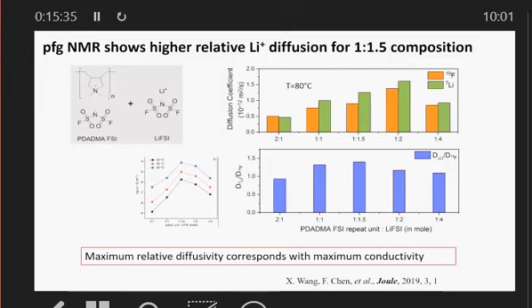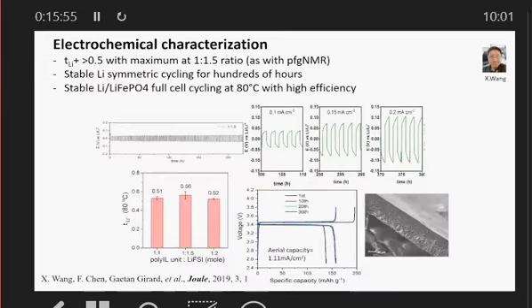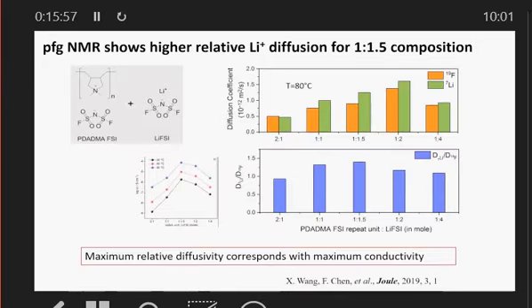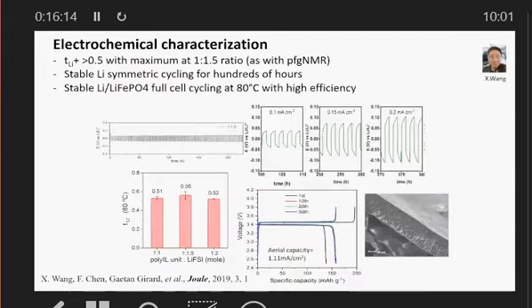We also see, in this case, unusually compared to the PEO-based systems, that the lithium diffusivity is higher than the anion. This would translate supposedly into a higher apparent transport number. Now, we're not measuring this under electric field, so it's just normal diffusion conditions. And so we are definitely seeing that we have a higher diffusivity for lithium. And when we do the ratio of lithium to anion diffusivity in the purple bar graph, we see that we have an optimum at around 1 to 1.5, which marries up with the optimum conductivity that we see. So can we understand this further?